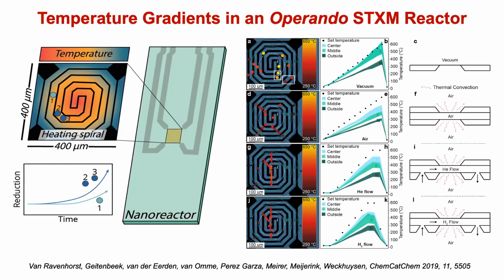Then we set the temperature, and we do it in vacuum. The center and the set temperature behave rather well. You see the top right? It's not bad, but it's vacuum. Then you do air, and then you start to flow hydrogen or helium. The message here is: you set the temperature, but you will never reach the temperature you set locally.